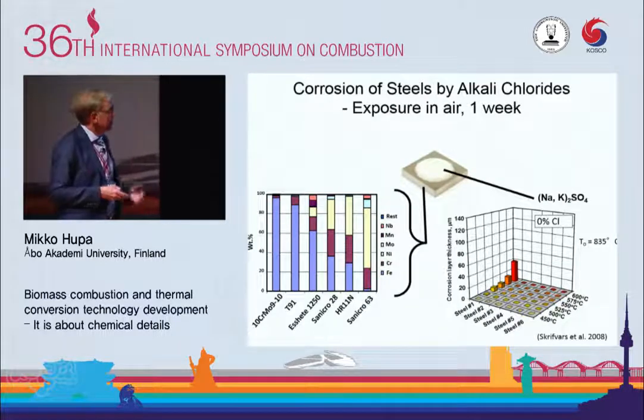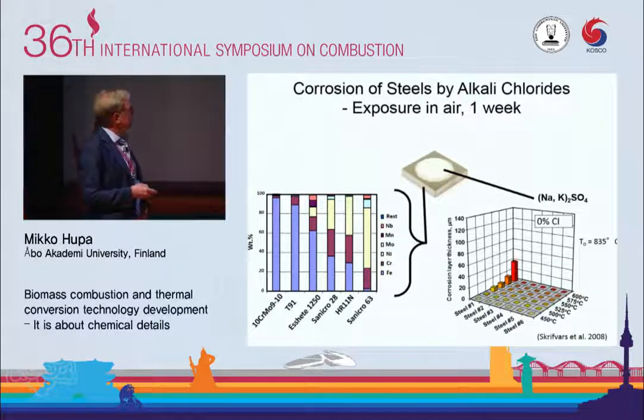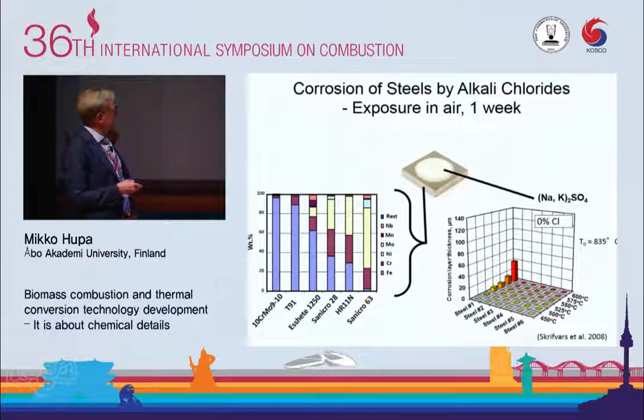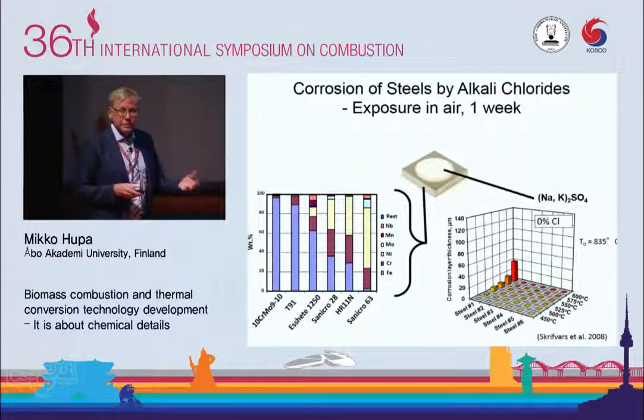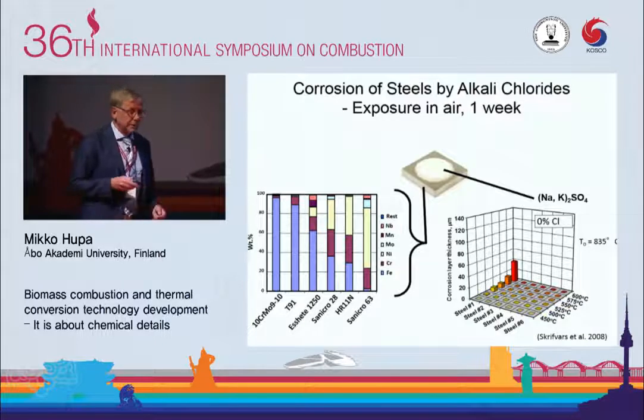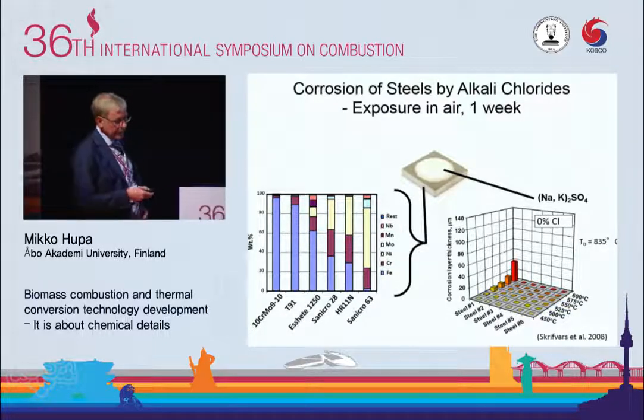And here I show one quite big study we did a while ago where we compared 6 different steels for chloride-induced corrosion. 6 steels, starting with carbon steel, with most of it iron, and then going nicely, they are commercial steels, but systematically going to more and more advanced. These are austenitic stainless steels, and these are high alloy nickel materials. It's good to know here that if this costs 1, this will cost about 40. So they are extremely expensive ones, because of the quality of the steel and the nickel content.